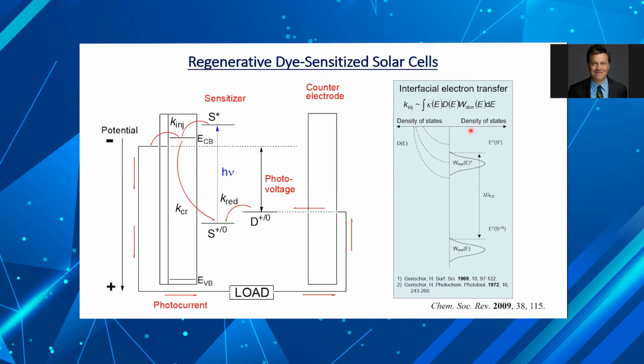And one thing I will come back to is that when Gerischer looked at these kinds of pictures in more precise detail, he really emphasized distributions and the overlap of the sensitizer with the unfilled states in TiO2, for example. And he also showed that these states are not fixed and can change based on the environment. For a single crystal material like TiO2, the band edges can move 59 millivolts per pH unit when put in aqueous solution. So they move around and they matter.